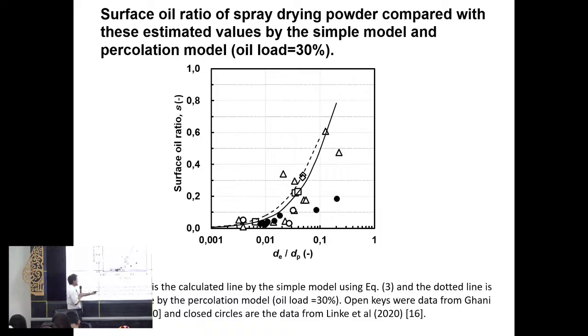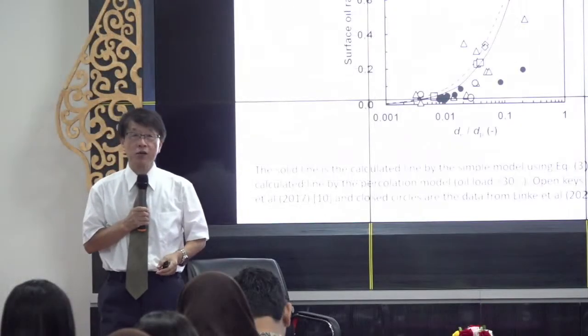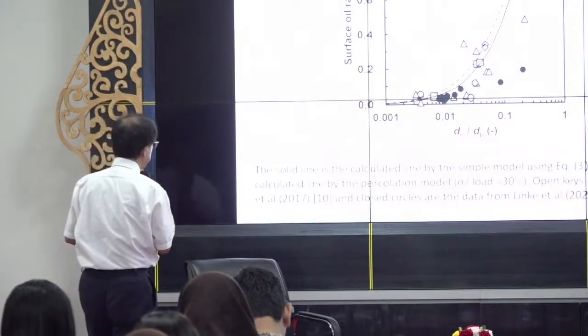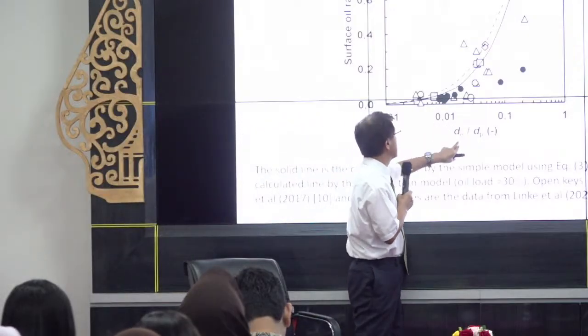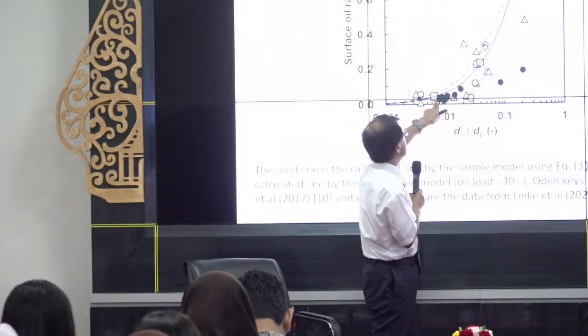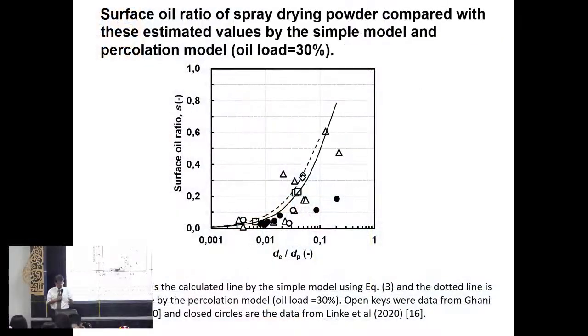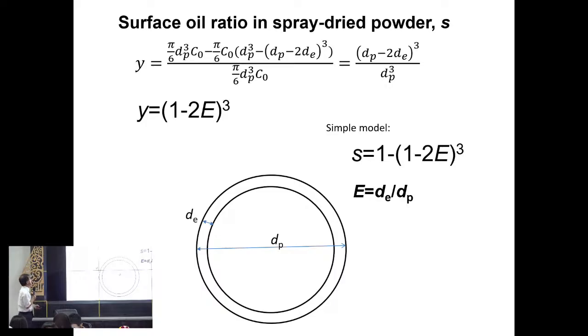Therefore, for example, in the case of a 1 micrometer oil droplet size and powder size below 100 micrometers, the ratio increases above 0.01, and the surface oil increases. This is a simple model for the surface oil ratio in spray dried powders. E means DE by DP, where DP is the powder size and DE is the oil droplet size. So we can estimate the surface oil ratio using DE by DP. Therefore, the average oil droplet size is important.